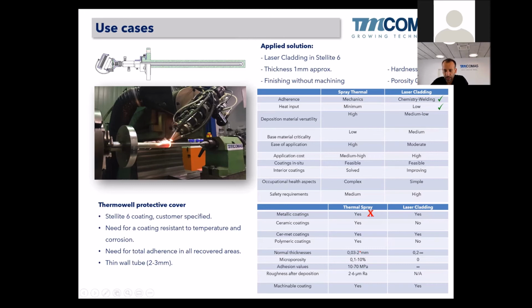So in this case, we choose to use laser because we need Stellite coatings. The Stellite coatings applied by thermal spray are not so good. There is some porosity. It's difficult to make a good adhesion of Stellite 6 particles because Stellite 6 is a material that is not affected by heat, so it's difficult to deform. So by thermal spray, Stellite coatings are not very good. It's better to weld them, and the best way to weld is using the laser. So in this case, we have used the laser.